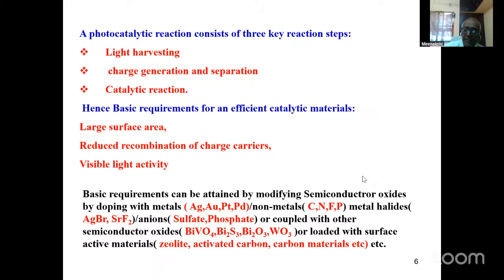Some of the semiconductors, if you take TiO2 or zinc oxide, have a band gap energy suitable only for UV light. So we can make this UV active photocatalyst into a visible active photocatalyst by modifying the semiconductor oxides. How to modify them? By doping with metals or with non-metals or anions, or even coupling with other semiconductor oxides, or loading with support materials like zeolite, activated carbon, and carbon materials. So these are some of the modifications which can be used for making the photocatalyst very efficient, that is, increasing the surface area, reducing the recombination, and also making them visible active photocatalysts.